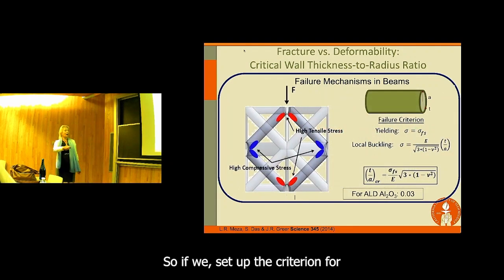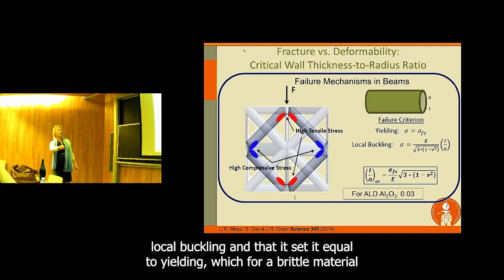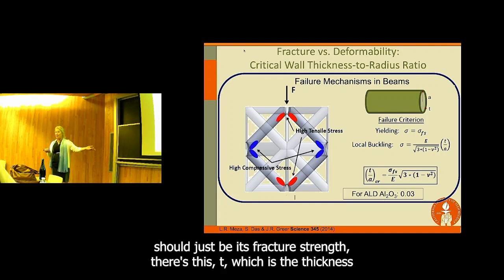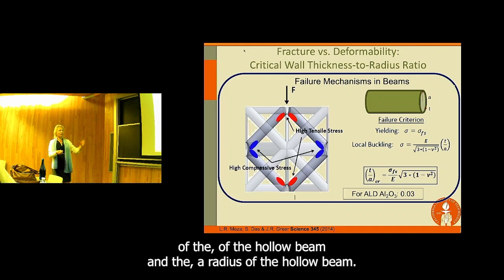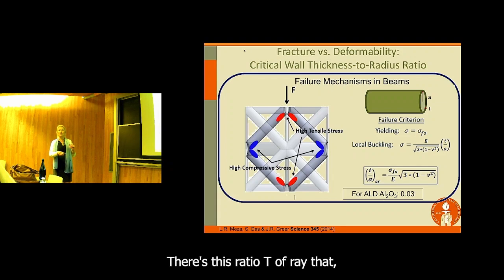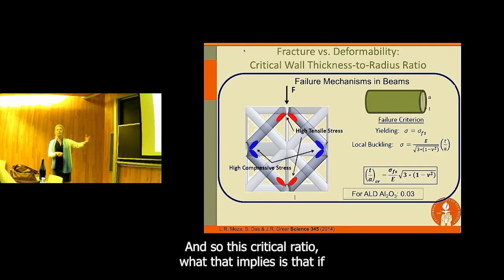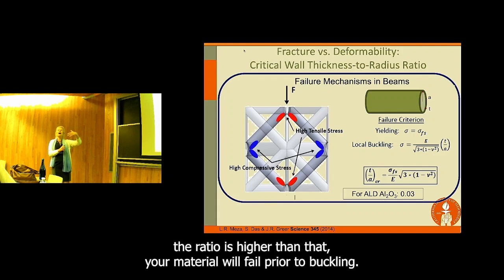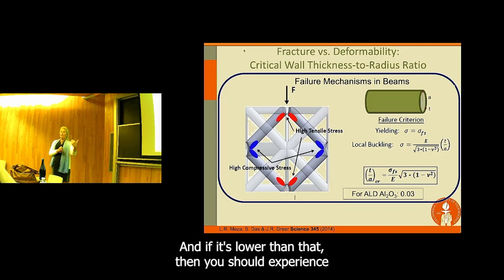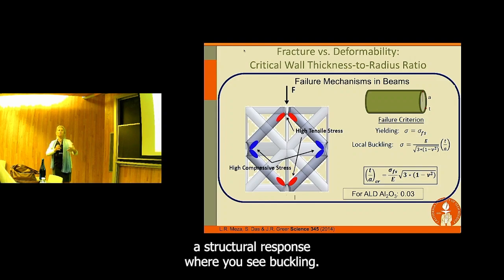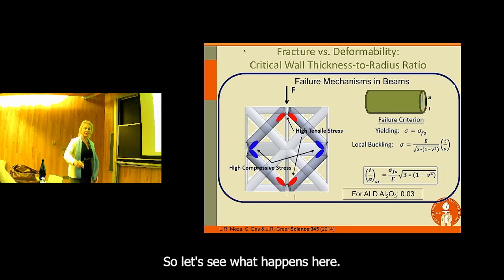So if we set up the criterion for local buckling and set it equal to yielding, which for a brittle material should just be its fracture strength, there's this t, which is the thickness of the hollow beam, and the a, the radius of the hollow beam. There's this ratio, t over a, that can be calculated. And what this critical ratio implies is that if the ratio is higher than that, your material will fail prior to buckling. And if it's lower than that, then you should experience a structural response where you see buckling. So let's see what happens here.